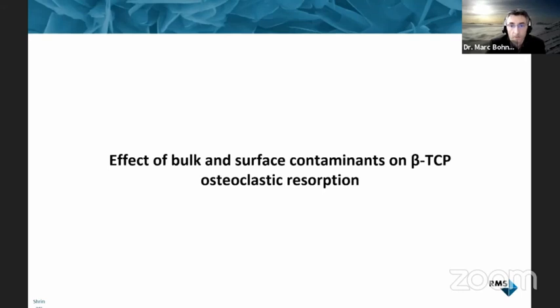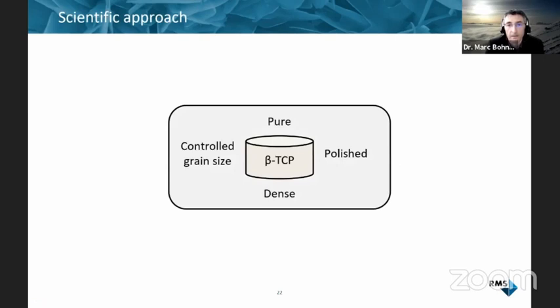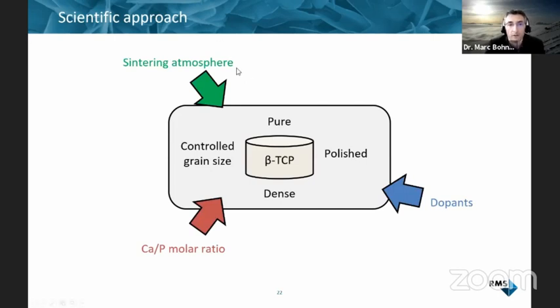And I would like to move to the osteoclastic results. So the idea was to take a dense, pure beta-TCP, to polish it to have a controlled grain size, and to use that as a control, where we would then look at the effect of sintering atmosphere, calcium to phosphate ratio, and also dopant. We did some tests with magnesium, with copper, with strontium, and I will only show results with copper because strontium had no effect and we had too little data with magnesium.